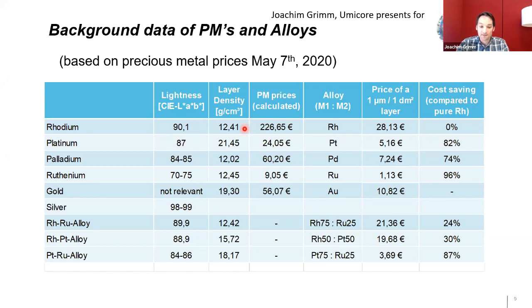So one point you always have to be careful about if you do some calculation. If you do plating with rhodium or you buy it, it's always by weight. And this depends totally on the specific element's density. The layer density of pure rhodium is 12.4 compared to platinum, which is 21.45. So in your calculation, when it comes to the thickness of a layer, you have to calculate with the layer density. But this is all needed for the final calculation.